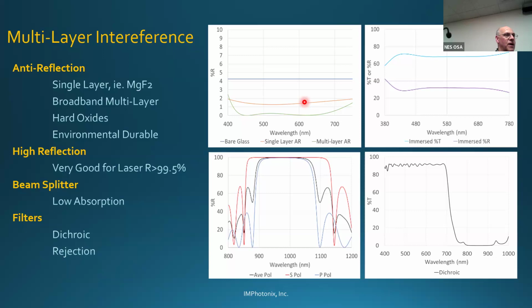Again, based on the thickness, you can tailor this for any wavelength. And mag fluoride has a very broad wavelength band, so you can actually use it for AR coatings in the UV and the infrared. And then finally, if you do a 3-layer design, you can get even lower reflectance and a very broad bandwidth. Going down, if you want to design a 25 layer coating, you can get better than 99.5% reflectance. Each layer is designed for a specific wavelength based on the thickness. And I'll explain that more later.